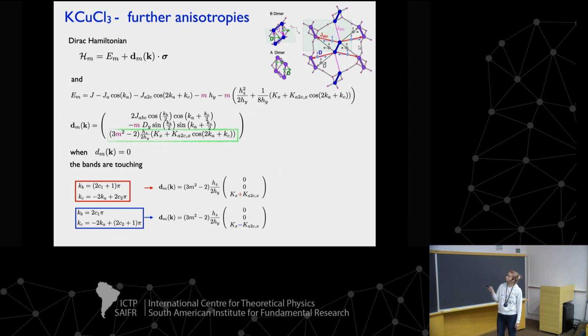And what happens when we tilt the magnetic field and take these into account? These are actually small parameters. But as you can imagine, my original big Hamiltonian that was block diagonal is not going to be block diagonal anymore. These terms will mix the different SY components of the triplets, but one can do a canonical transformation to get rid of these couplings, take them into account perturbatively, and still keep this SY plus minus 1 and 0 basis.